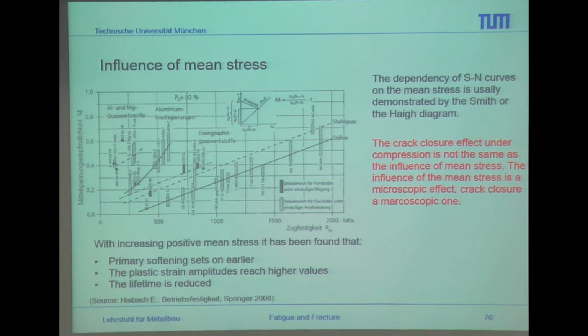So for example, for materials which we use for daily design in Europe, this is the ST37 and the ST52, which have a yield strength of 235 megapascal or 355 megapascal. And you see here that the mean value effect is really low, but also you can take this influence into your design, which I'm going to talk about tomorrow. At this part, you have some small influence. This is really low. But if you go for some other alloys, like titanium or cast materials, the effect increases much more.